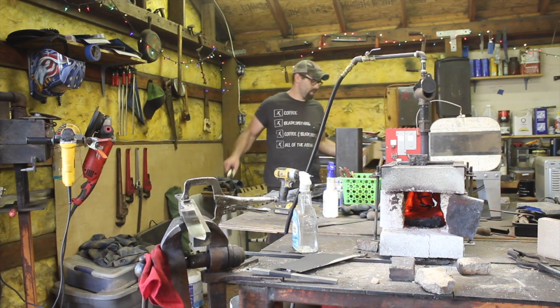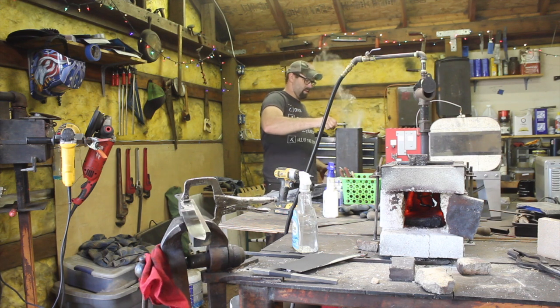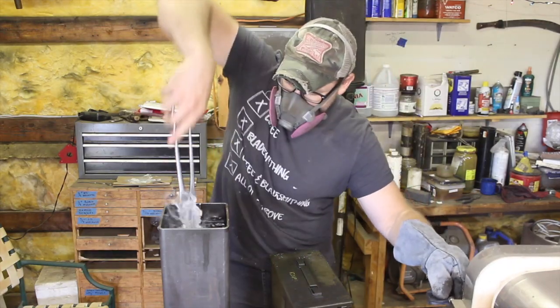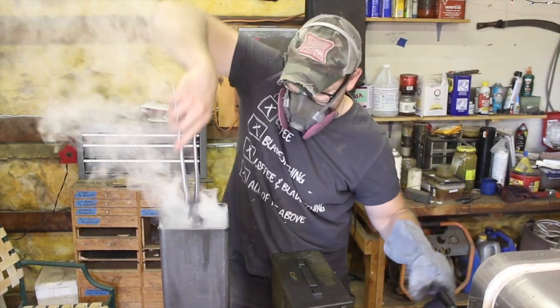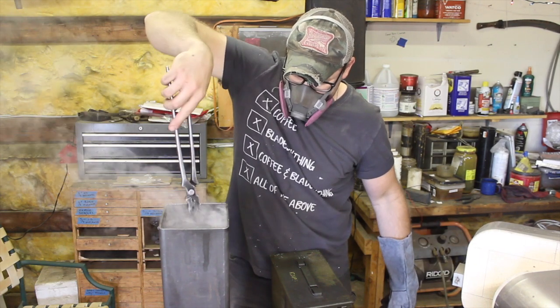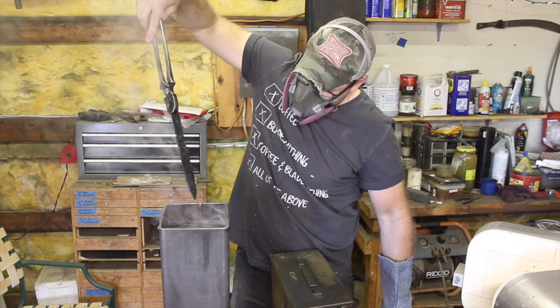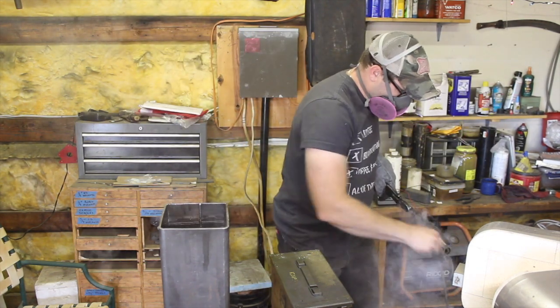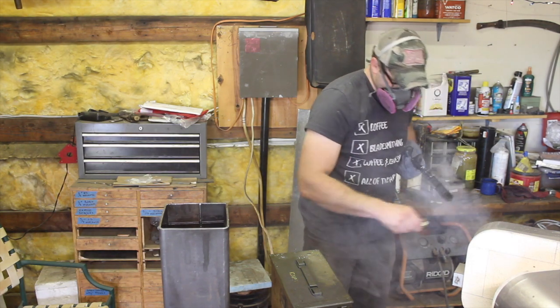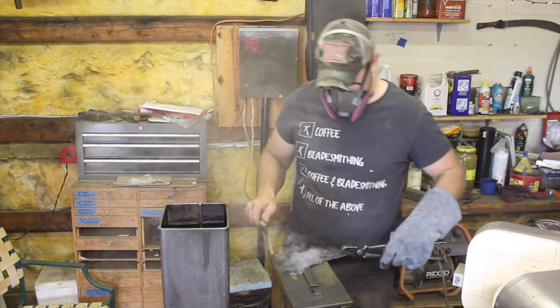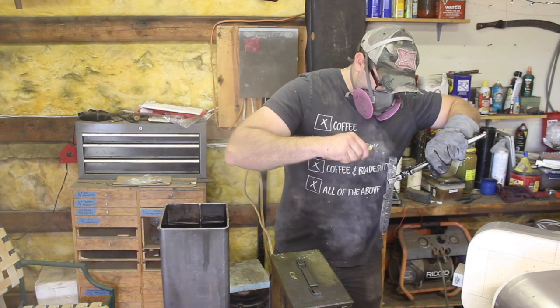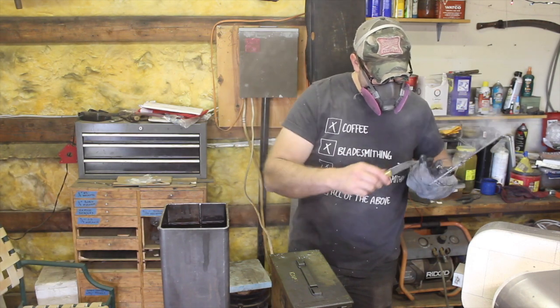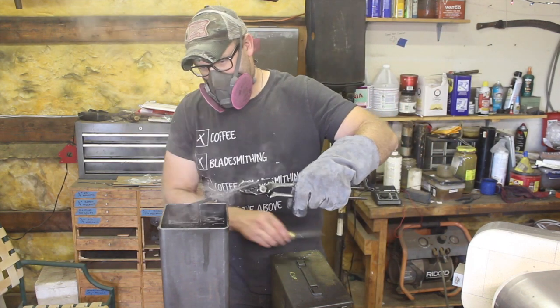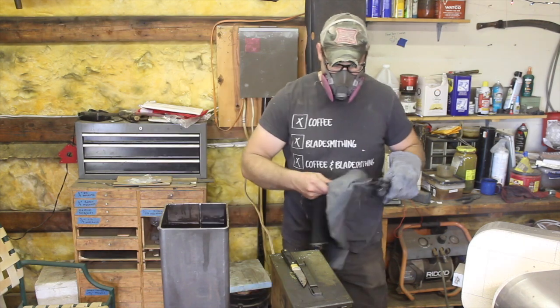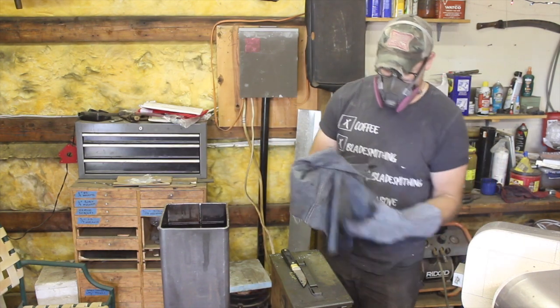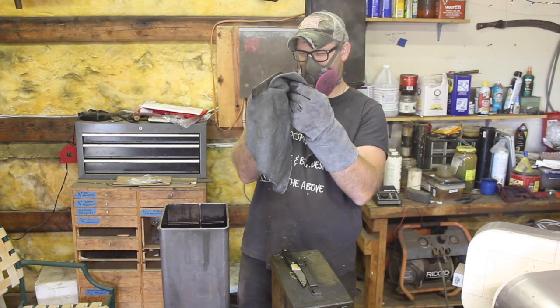I like to do it so that there's less material between the finished edge and the quenchant, so we get a good cooling rate. Quenching the blade here, you'll notice I don't keep the blade in the quenchant very long, and that's because it's really just a matter of less than a second that the steel needs to cool from about 1485 degrees down to about 800 degrees. And then I take it out around 400 or 500 degrees, and it continues to cool, and I'll dip it back in there to make sure that it's still cooling down at a reasonable rate, but not super fast. That provides you with the best results, because you're not creating a whole bunch of unnecessary stress. The steel is still doing what it needs to do to reach full hardness.